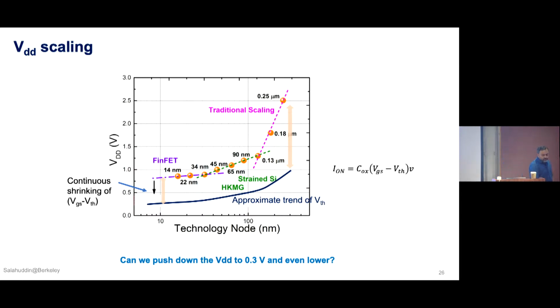If you now look at this VDD scaling curve, you can see that, as a first order effect, if I can increase this C by 2x, in principle I can reduce this VGS minus VTH by 2x. So we should be able to significantly reduce the VDD by going this way. One of the targets that we have set for ourselves is: can the VDD be scaled down to 300 millivolt or even below? That's something that we want to do. Again, I'll come back to that in 3-4 minutes.